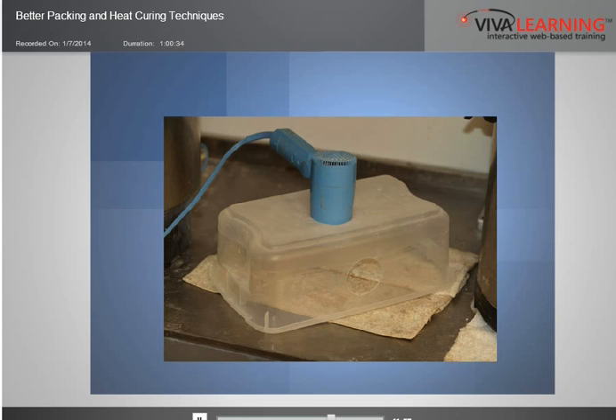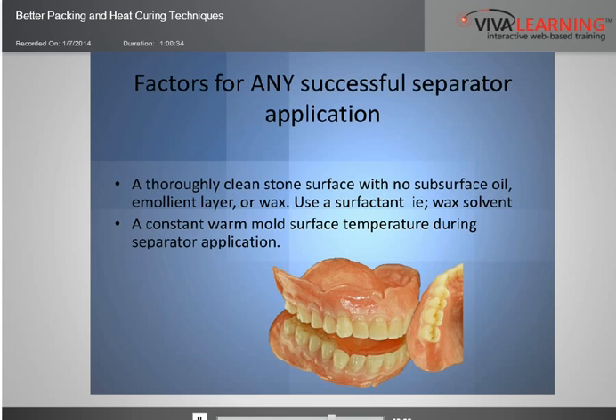Factors for any successful separator application, and we just talked about it: a thoroughly clean stone surface with no subsurface oils. I'm telling you, if you're using stuff with emollients that softens your hands while you do dishes, get it out of there. Don't use it, because it's got a softening agent which shows itself as an emollient. It's going to cover the necks of the teeth, and they're going to be popping off. Or you're not going to be able to get the separator to soak into the surface because the emollient's going to block it. There's oil in wax, so you've got to get rid of subsurface oil. I say use a surfactant, also known as a wax solvent. We have non-flammable wax solvents that we clean our tanks with. I use a little squirt of that in my mold along with some scent-free soap.